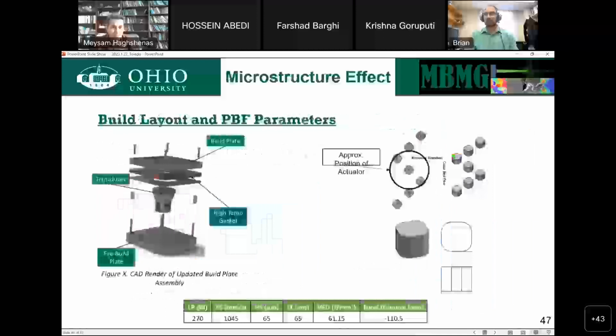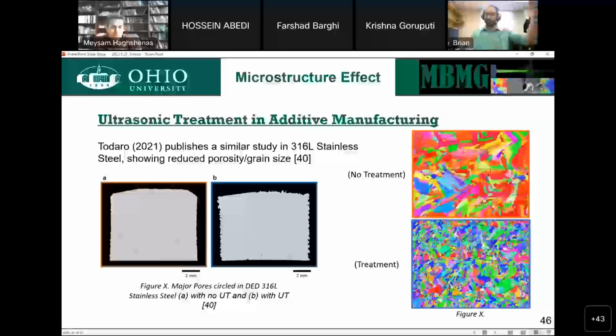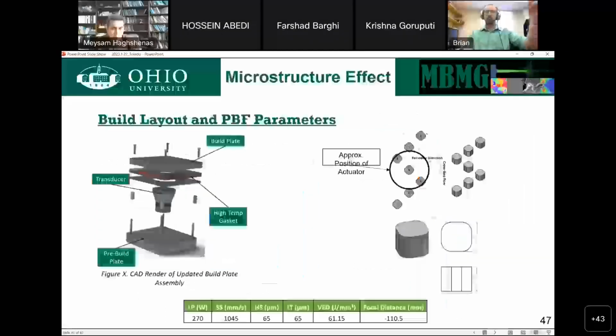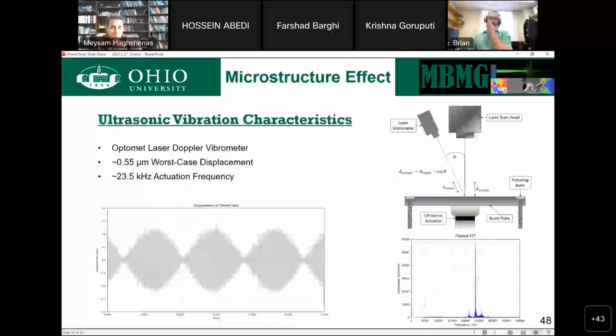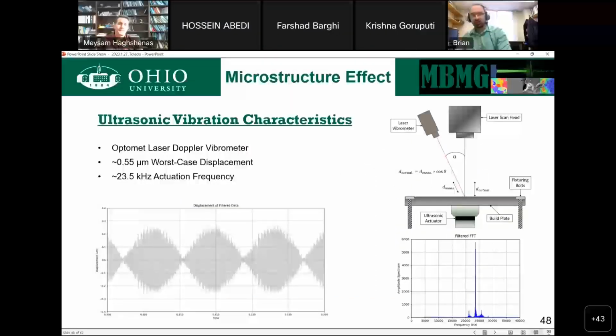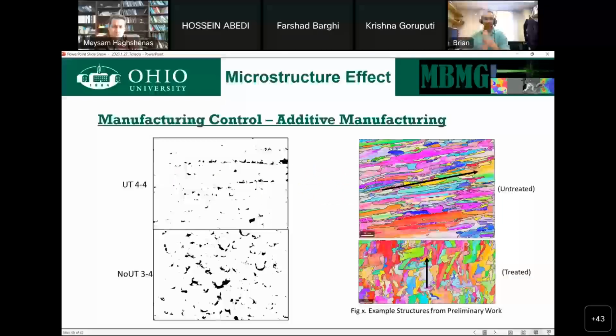In some cases with higher intensity, you see grain size change more. In our case, we're not. So there's two theories about what's causing this to happen. One is cavitation. There's wave streaming effects, there's cavitation, there's others. The prevailing theory is cavitation. It comes from casting theory, using ultrasound in order to get grain refinement in casting. It's the same premise that led to this.